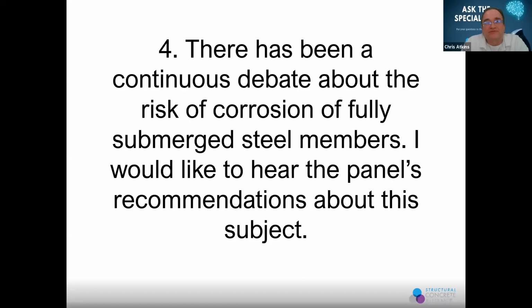For me, there's a relationship between corrosion and oxygen availability most of the time, which is why, frankly, they could find the Titanic, because if you think about it, that's been sat at the bottom of the ocean for 110 or so years, but still existed. So the corrosion rate does depend on oxygen availability, and when it's permanently submerged, there's less oxygen. That being said, in some environments, you can get microbial induced corrosion, which gives you a much higher corrosion rate. So most of the time, it's not a problem.